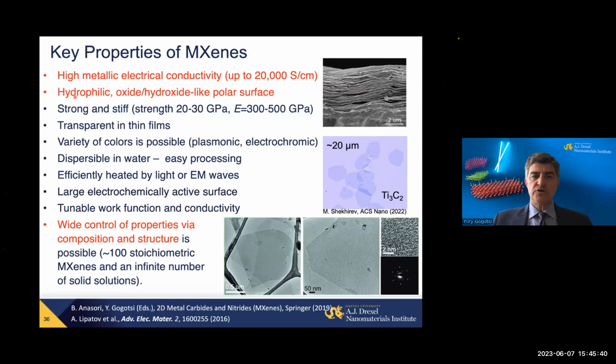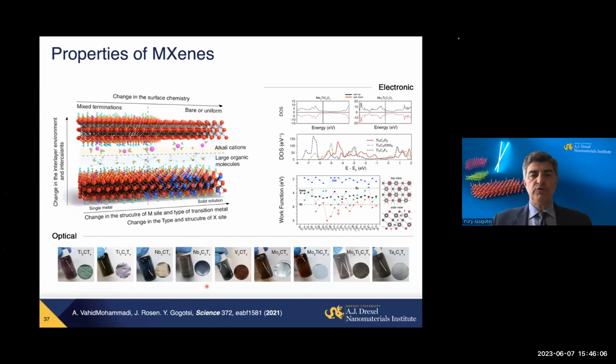But keep in mind, the combination of metallic conductivity and hydrophilicity is truly unique. And they're stronger than other solution-processed 2D materials. They also come in a variety of colors, and you have seen them. Transparent thin films, electrochromic films, plasmonic applications, and many others are enabled by this. And of course, today, I won't be able to go over many applications and properties. But again, one very, very important feature: all those properties are not given to you in one material, where you just get graphene and it's conducting, and you get boron nitride and it's dielectric and it is what it is.